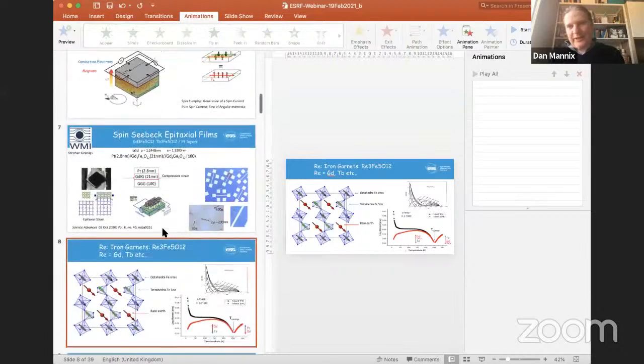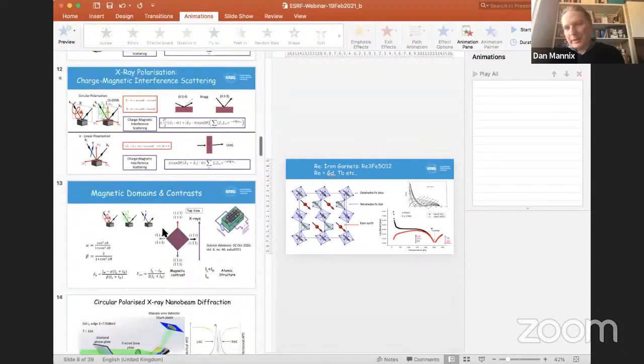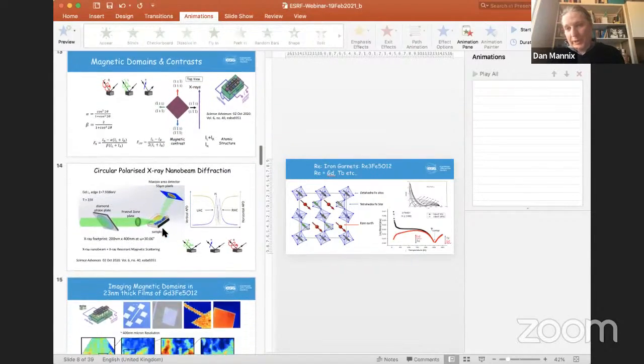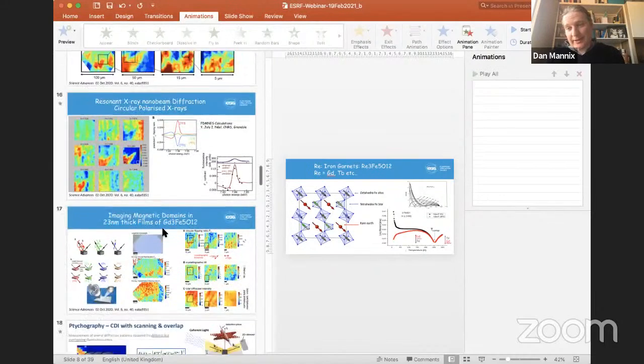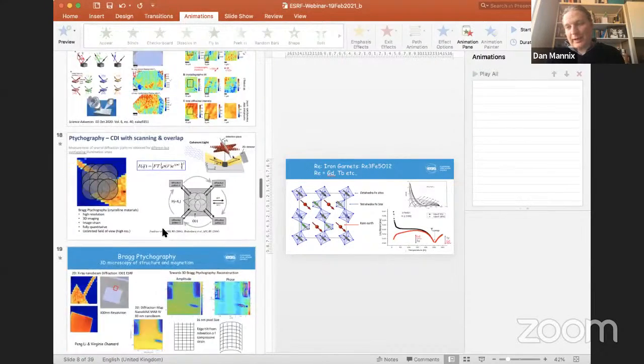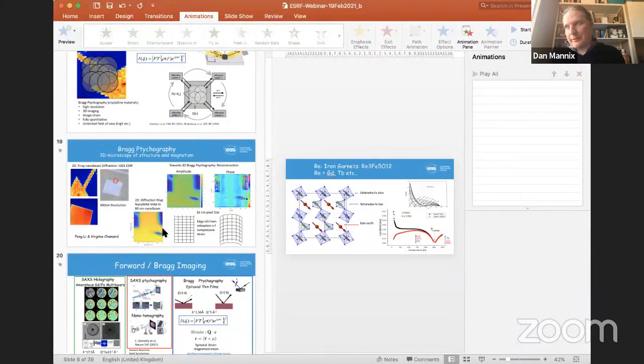Yes. So in fact, the neutron measurements that I showed, and actually the RIXS data, were all taken in applied field. For the neutron data, we have an electromagnet inside a cryomagnet. For the RIXS measurements, we used a permanent magnet. The samples are mounted onto a permanent magnet, and that's enough to saturate the moments along the 111 direction. It's very soft, the 111 direction.